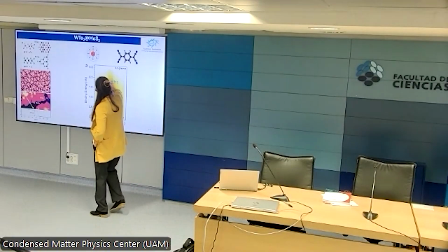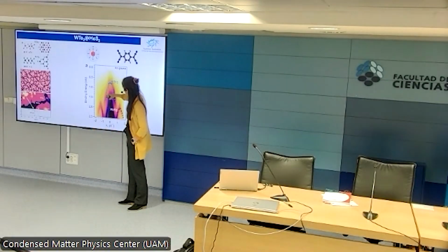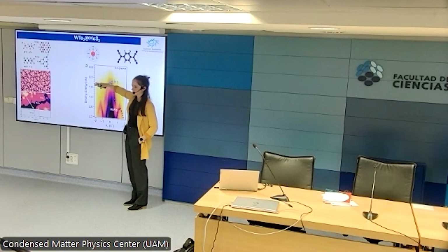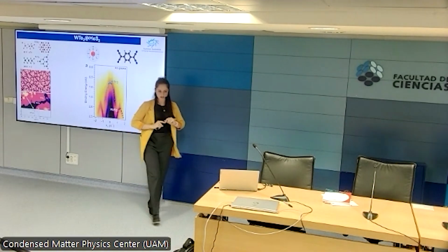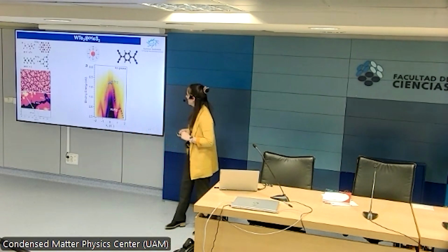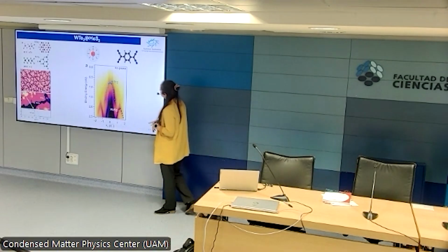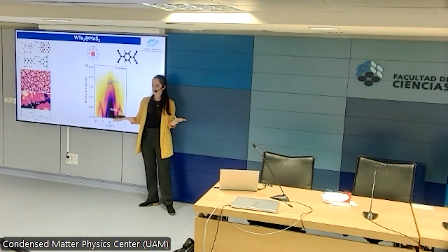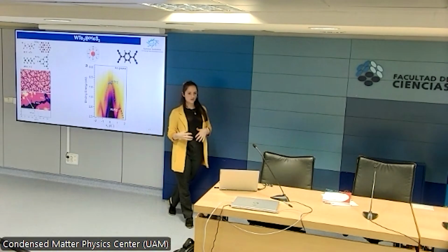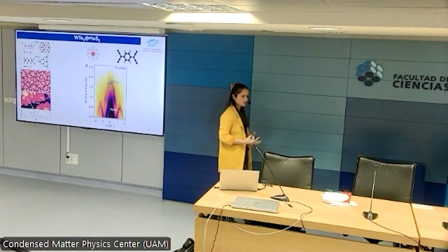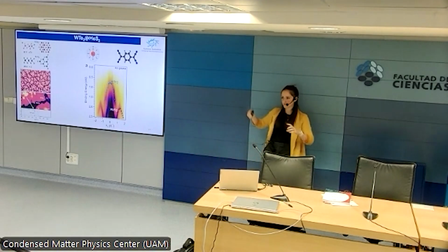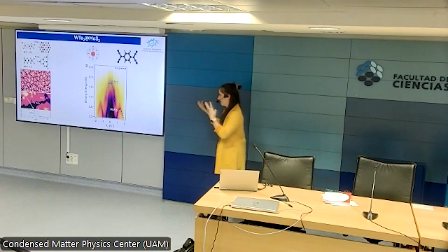So we grow it, and you can see MoS2 has states here, but there's a large area where MoS2 doesn't have any density of states. It's a wide band gap. It's the perfect substrate, we thought. So we grow tungsten ditelluride on MoS2, and we thought we'd start putting on potassium, which is an electron donor, or F4-TCNQ, which is a molecule which is an electron acceptor, to try and shift this band structure and eventually see something happen in the band structure.